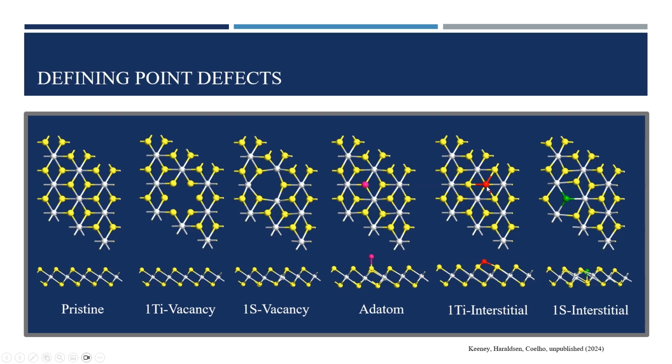Specifically, we look at the single titanium interstitial. While this was initially right here in that plane of titanium atoms, the titaniums all have 4 additional electrons, and so they're not going to bond incredibly strongly, especially relative to how they'll bond with the sulfur, which has that -2 oxidation state. And as such, you find that the titanium is going to settle right on top of that sulfur plane, such that it can maximize the attraction between the titanium and the sulfur and minimize the repulsion between the titanium and titanium. And even then, you notice that some of these inner atoms are shifted around. So for the sulfur vacancy, you find that these titaniums are shifted, and especially the sulfur interstitial is a little funky.